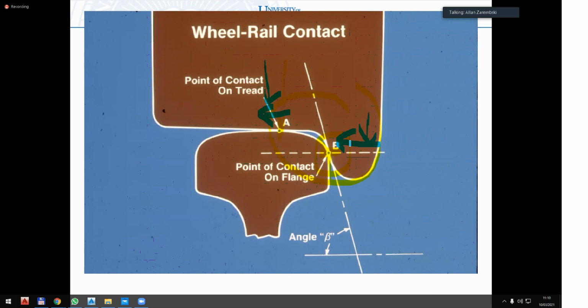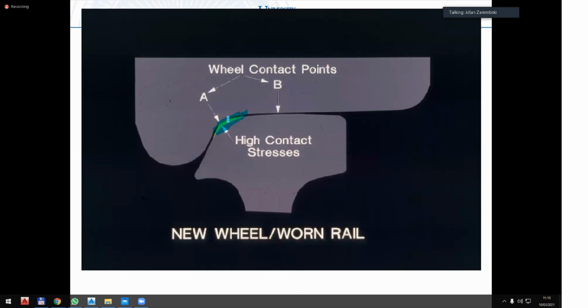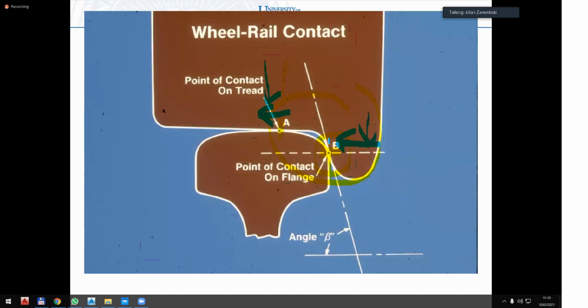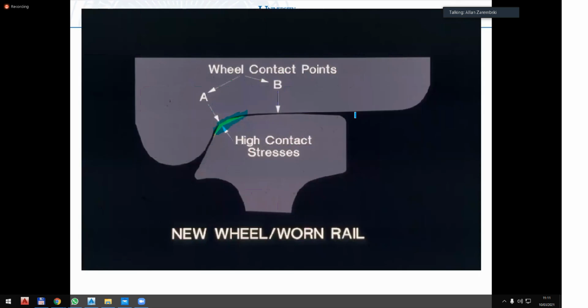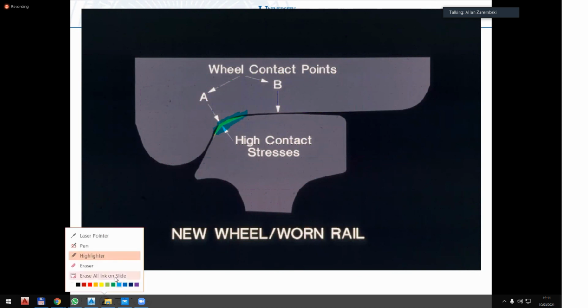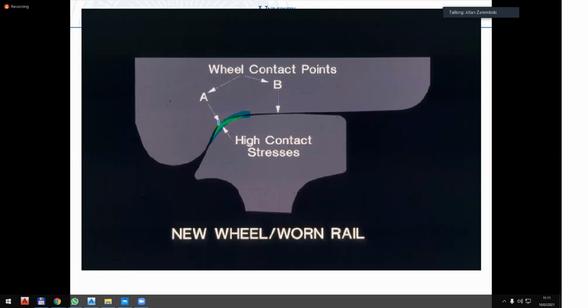In metros, where the load level is a little bit lower, you sometimes will prefer one-point contact, because in two-point contact, you're basically trying to go around the curve with two different contact points. This is actually going to generate a slightly higher lateral load. So for a lower load environment, such as metros, sometimes a one-point contact is more desirable. We'll talk about this a little bit more when we talk about profiling, but what you're going to tend to do is try to get a distributed contact that looks like this. That would spread the load a little bit, but still not have the very high contact stress.